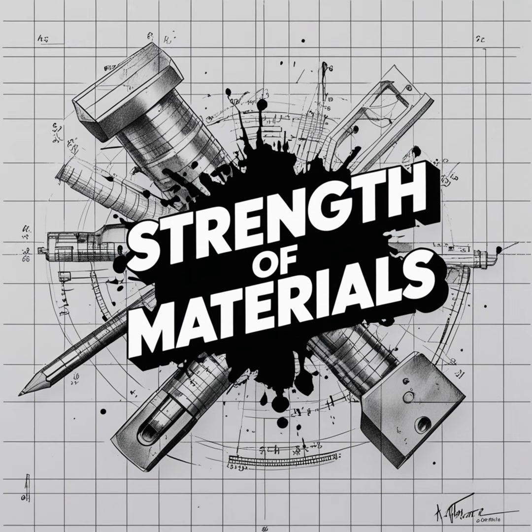Imagine a steel component. Yeah. From our SN curves, we know that if we subject it strictly to a high stress, let's call it stress level A, it will snap at exactly 10,000 cycles. Okay. Now, in the real world, the part only experiences 1,000 cycles of stress level A before the load changes. What have you done? You have consumed exactly 1/10 or 10% of its total life. Right. A simple fraction. 1,000 divided by 10,000.